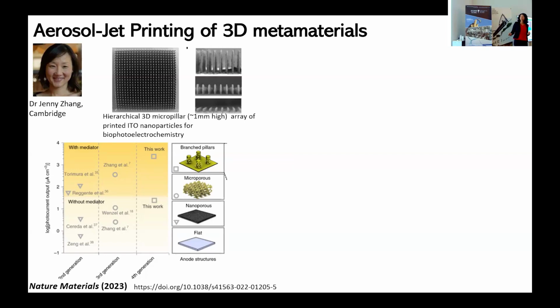And typically the way people would do this is you have a flat conducting substrate and you put your cyanobacteria on top of it. You get some photocurrent out of it, but not very high, because at the end of the day, you want more coverage of the bacteria. So what's the next thing you can do? You can make them nanoporous or microporous, basically increasing the surface area so that you have more bacteria attaching to your electrodes. What we showed was that, using aerosol-jet printing, we could make these 3D structures. And by playing around with the processing parameters, you could include porosity. So it was like a hierarchical 3D micropillar.